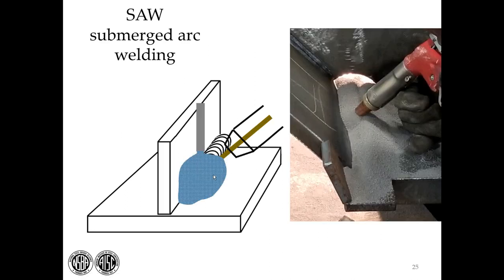And then finally, we come to submerged arc welding. In this case, once again, you have a shield, but the shield is not a gas or something burned from the consumable, but rather powder that's delivered from a tube that comes down. So when you're welding with submerged arc welding, as you progress, the tube progresses with the welding gun, and flux drops out. You'll see a lot of flux here to make sure that there's good coverage. The flux that's not burnt up in welding is swept off and reused. So the welder progresses and delivers flux, and the welding is accomplished.